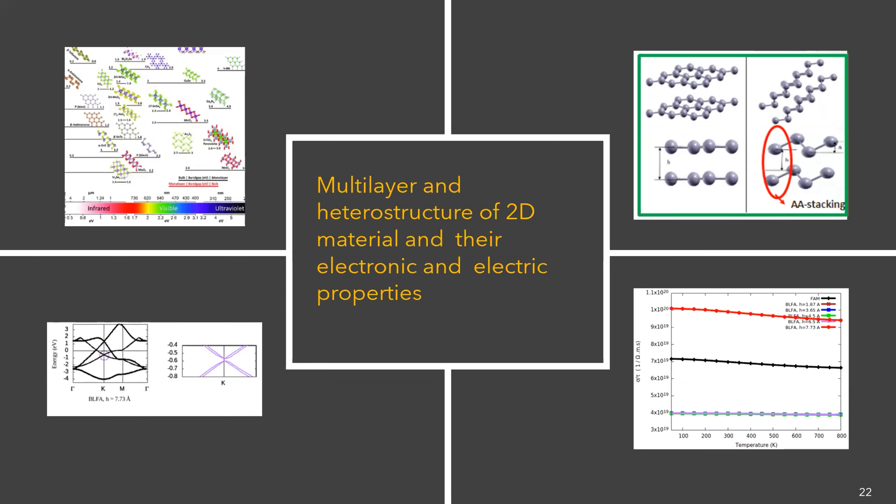The multilayer and heterostructure of 2D materials and their electronic and electrical properties are also studied. We present in the following some conclusions in this study. The multilayer effect is visualized in an opening energy gap in the flat bilayer and the energy gap in bilayer decreases with the increase of interlayer spacing.